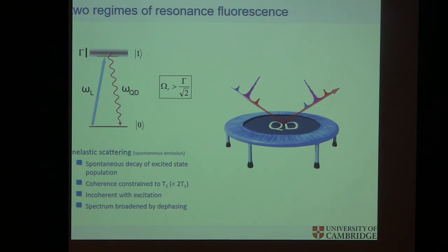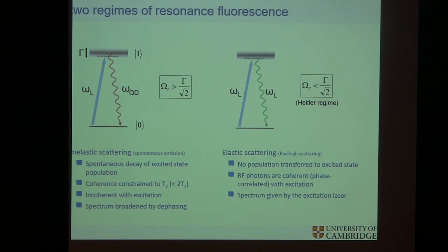So there's a very simple answer for that, and the simple answer is actually elastic scattering. If you're operating in a regime in pure quantum optics where your excitation with light is not too strong, then you can operate in this regime where the scattering is dominated by elastic scattering. The light generated is mostly elastic. What does that mean? It means you're not constantly going to an excited state and then waiting for a decay. You're actually scattering a laser photon into the environment, into other modes, without really changing its properties. There's fine-tuning in there that I'm skipping, but essentially you get something that looks like a laser and walks like a laser.